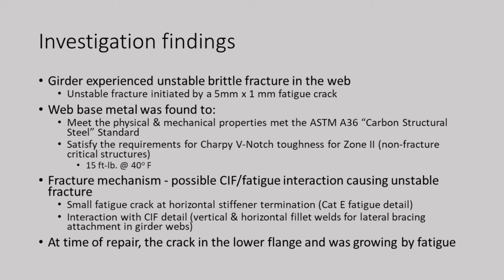Well, we know that unstable brittle fracture started and it ran from a little fatigue crack 1 millimeter deep by 5 millimeters wide. We performed tests on the A36 material. We looked at the physical and mechanical properties, did some tensile tests, did what they call EDS, which is a spectrographic method to check the elemental content of the steel. And we found that it conformed to A36 structural steel.